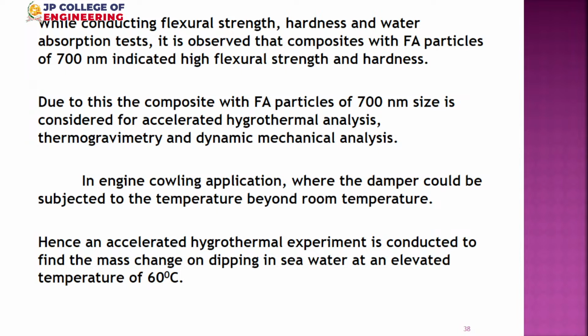Then we wanted to check at a high temperature. Therefore, we say even at a temperature around 60 to 70 degrees, that's what is normally encountered in the bonnet of your automobile. So we heated up the seawater, put the samples in, and checked the water absorption at the high temperature. This is the accelerated hygrothermal test. Next slide, please.